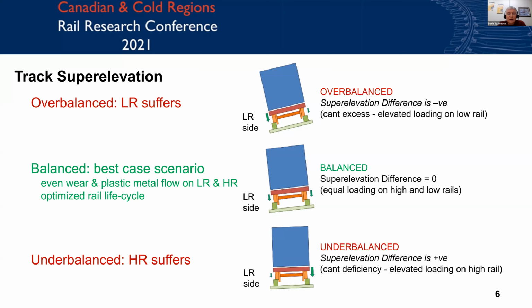Most of the time, you either have an overbalanced condition or an underbalanced condition, and either one of them destroys the rail where the load is highest. So for example, for the overbalanced condition, you have a cant excess, and you put too much load on the low side of the rail, and therefore you have more plastic flow in that location. You have more damage on the low side.